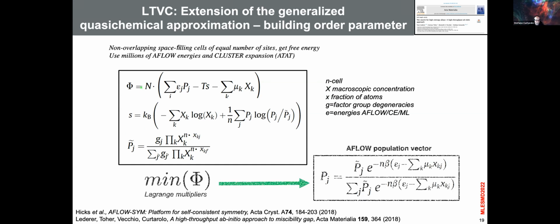Okay, and now let's do it. So how do we solve this problem? It's very simple. Lagrange multiplier. So you minimize everything and you get this, which is the AFLOW population vector. This is exactly the population vector that I told you before, where this is the activation energy. But now there is this part. Okay, so this is the Gibbs part. So instead of being a Boltzmann population vector with a Boltzmann probability, this is a Gibbs population vector with a Gibbs probability. Okay, and therefore you can change the concentrations and go off stoichiometry, and instead of going up and down the phase diagrams, you go left and right and find pretty much whatever you want, the solvus, etc. Right? There is normalization, but forget about it.